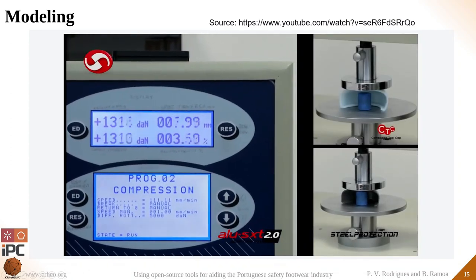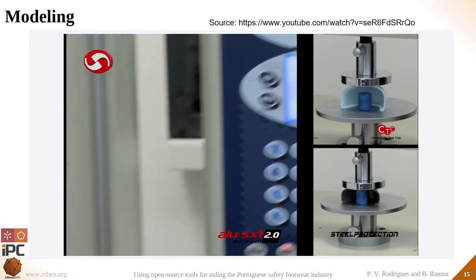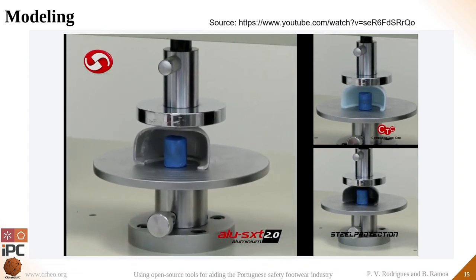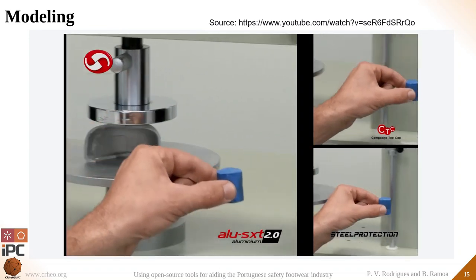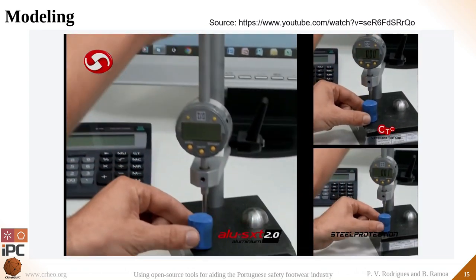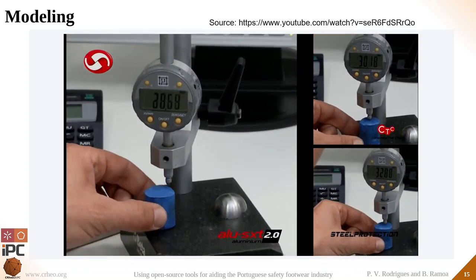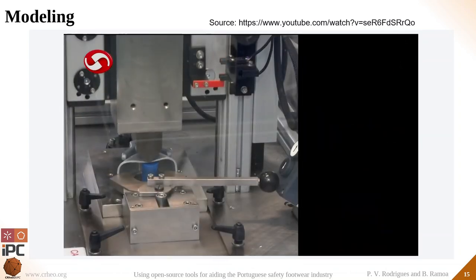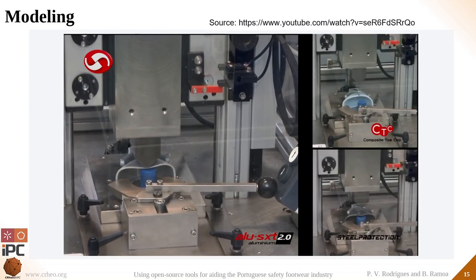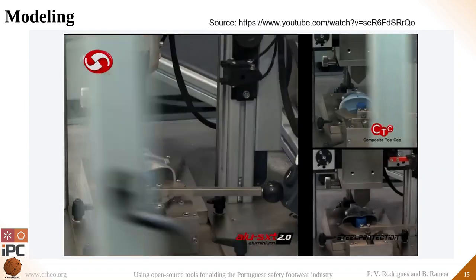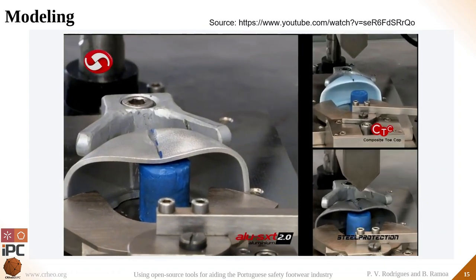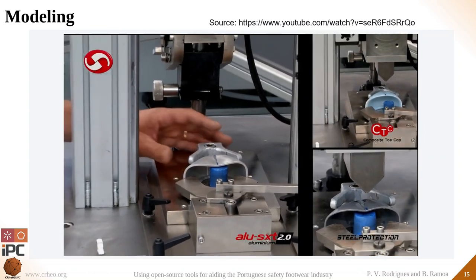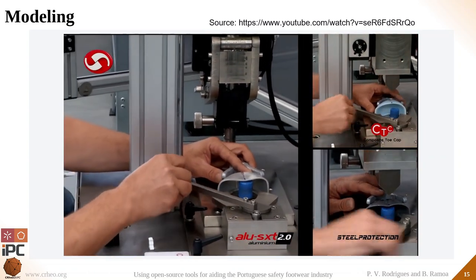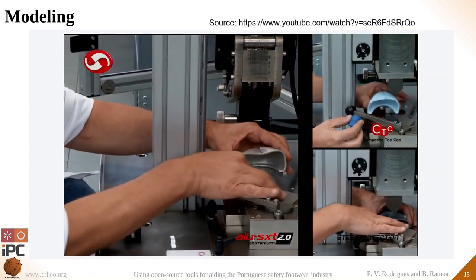And here we present a video which illustrates the compression and the impact tests. For each test, a cylinder of clay is placed inside the toe cap, which measures the total deformation of the toe cap. On the compression test, a plate is used to compress the toe cap up to 15 kN force. And in the end, the total deformation of the clay is measured. For the impact test, a free-falling striker is placed high enough to have a total impact energy of 200 joules. And in the end, the deformation of the clay must be within the standardized values. And this value is equal to the toe cap clearance.